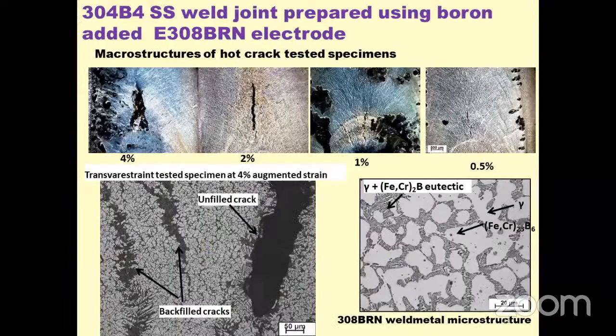So now we have seen how this cracking is occurring while using a boron-free consumable. Now let us see the performance of the boron-added consumable. These are the macrostructures of the tested specimen at various strain levels. You can see that if you increase the augmented strain, the crack width and length increase. But it has certain cracking resistance up to 1% augmented strain. If you go beyond 1% augmented strain, the material is prone to cracking.